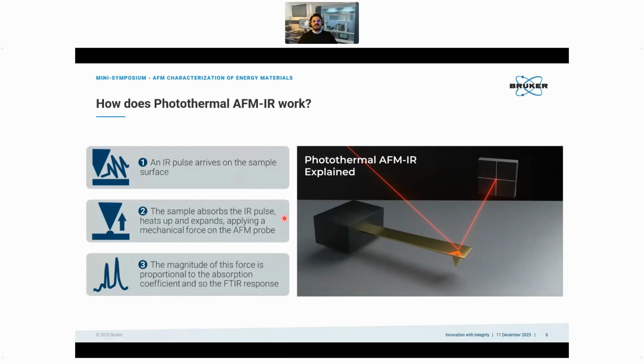From the perspective of the flow of the measurement, we will be sending infrared light, focused onto the surface. This light, if absorbed, will cause the surface to deform, to expand due to local heating, which we call photothermal absorption. This deformation of the sample, we actually know very well how to measure with AFM. And this will allow us, from the magnitude of this absorption, to reproduce spectra.